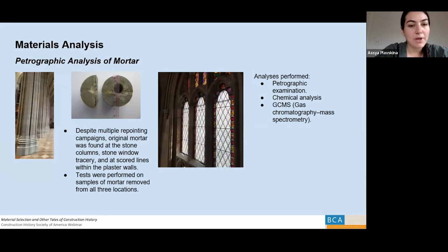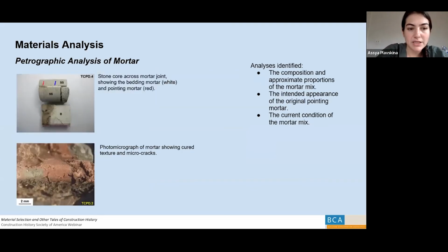We also took a look at the mortar. Now the interior and exterior of Trinity Church have been repointed several times throughout its lifetime, but we were really hoping to find some of the original pointing mortar, and we were able to do so. We found original pointing mortar at the window tracery. Historically, it's mostly been repointed, but there was some original pointing mortar remaining. Most of the columns had the original pointing mortar. And then we were also surprised to learn that we found pointing mortar within the scored plaster joints of the plaster at the walls. Oftentimes in faux masonry plaster finishes, the joints are painted in with a finish, but this time there actually was true mortar in there. And the goal of the analysis was similar to plaster, to understand the composition and approximate proportions of the mix. And then this would lead us into identifying the condition of the current mortar and to better understand a replacement mix for where it would need to be replaced.